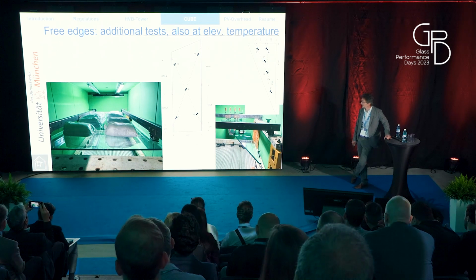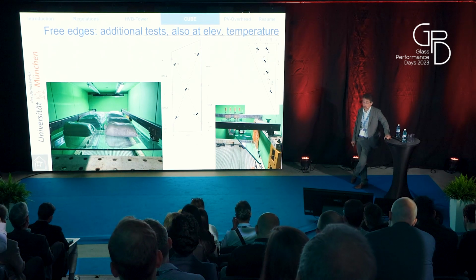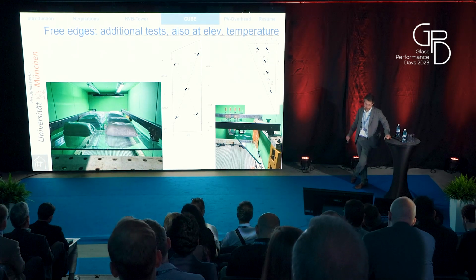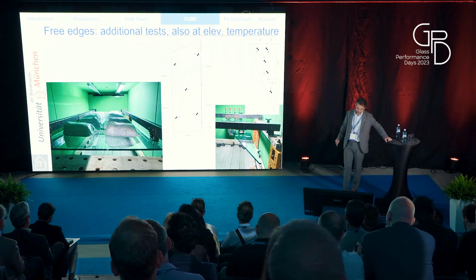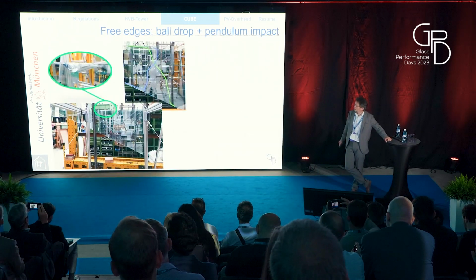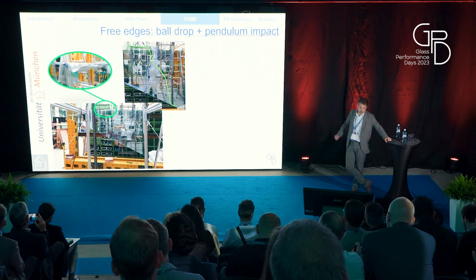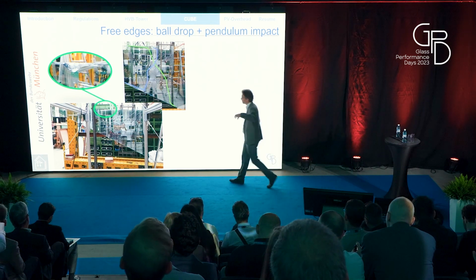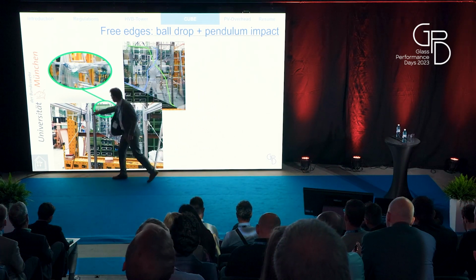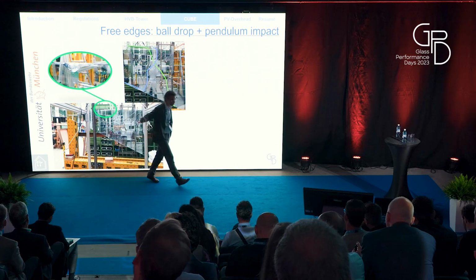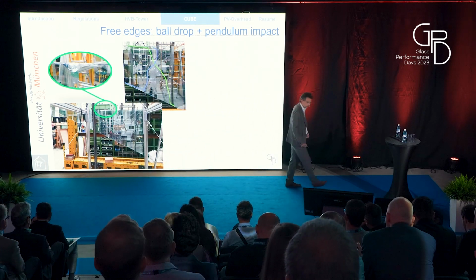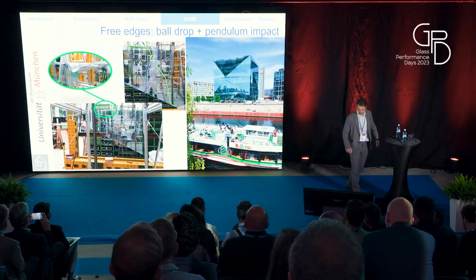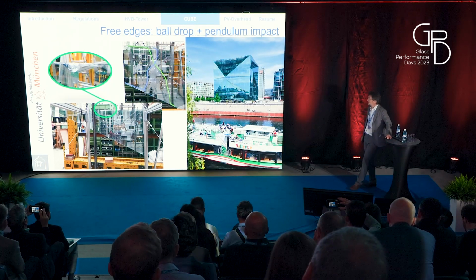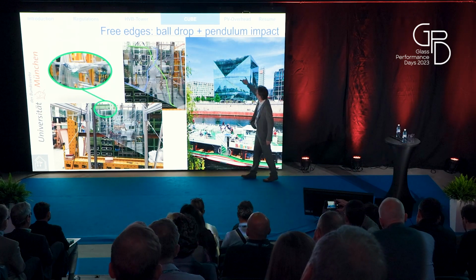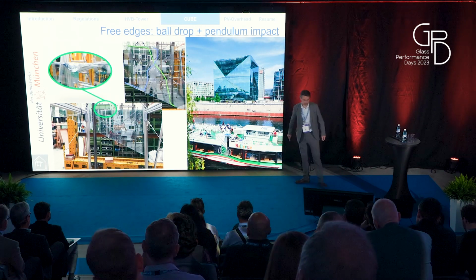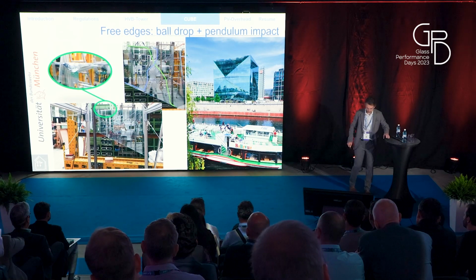We did further tests for residual strength, putting the samples in the climatic chamber and heating up, and it behaved well, luckily. Also for the balustrade situation, we had to do the ball drop test before the pendulum test. We throw a steel ball on the edge of the balustrade element, get a crack, and after this we did a standard pendulum test. Luckily, it also turned out positive. And that's the situation at the moment. So no edge protection, and you can see here a very perfect glass edge, if you can recognize it.